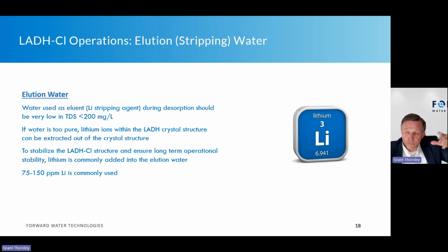The lithium goes into the voids. However, that lithium layer chemically requires lithium in that crystal structure. It's part of the crystal structure. So when you use water, it actually grabs and extracts lithium from that crystal structure and destabilizes it. So it can collapse the crystal structure over time.